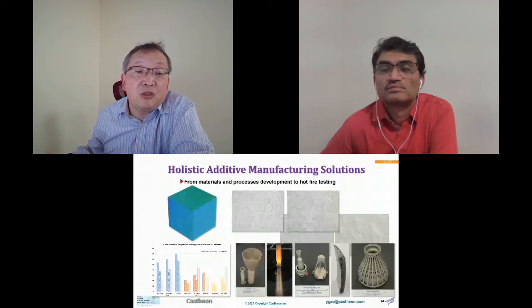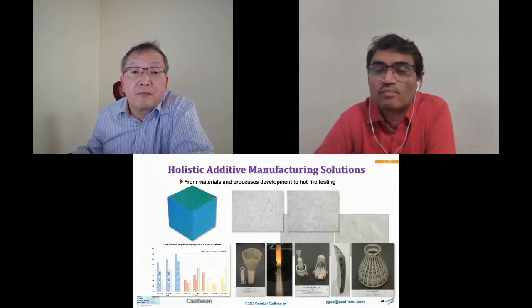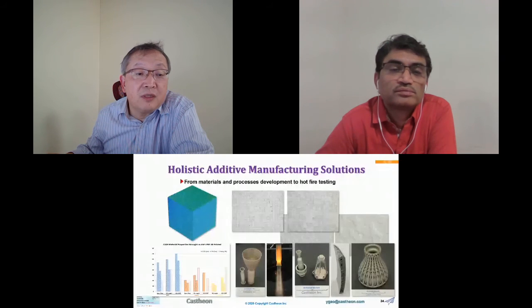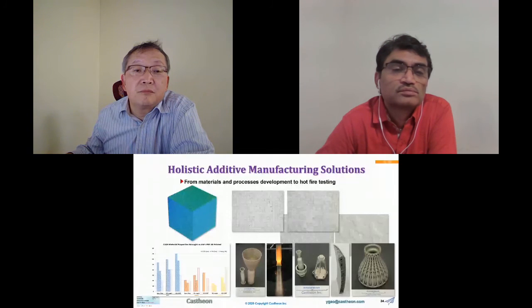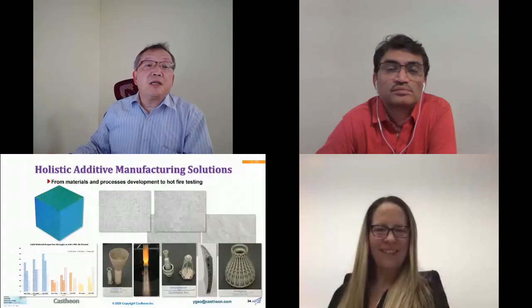So now going back to the high entropy alloy. I can get rid of the laser mode. Okay. And so this is the second generation high entropy alloy 6K, and Sunil has been working on it, and it's quite interesting. The first time we could make this, but it's not always really dense. And the second generation, what you can see is we can make this overall more than 99.75% dense, and the as-printed microstructure shows the properties. It's not bad, and so those are the things we have tried to explore using this process.